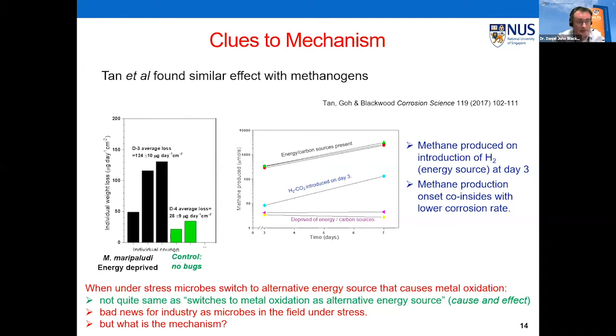So one of the things I wanted to do was to first prove that other bacteria other than SRB do cause corrosion. And we were able to do that with some methanogen work that I did several years ago. And over here, we see the weight loss. It's much higher with the bugs than without the bugs, the methanogen. And this was only found when it was starved. If we didn't starve the methanogens, we had no accelerated corrosion.